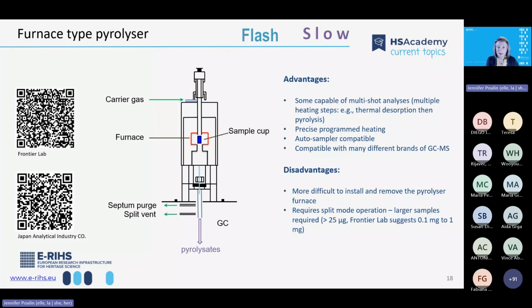And finally, this is the furnace type pyrolyzer. It heats a sample by dropping a sample cup into a preheated furnace. So there's many advantages. And this type of pyrolyzer is very well used and popular. It's capable of multi-shot analysis, so you can have multiple heating steps. In fact, I believe with the Frontier pyrolyzer furnace, the sample cup can actually be removed from the heating zone after it's pyrolyzed or been heated for that one time, and then you can put it back in for another heating zone, which I think is really great.